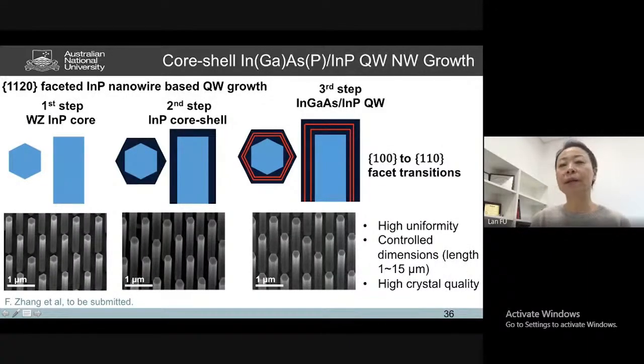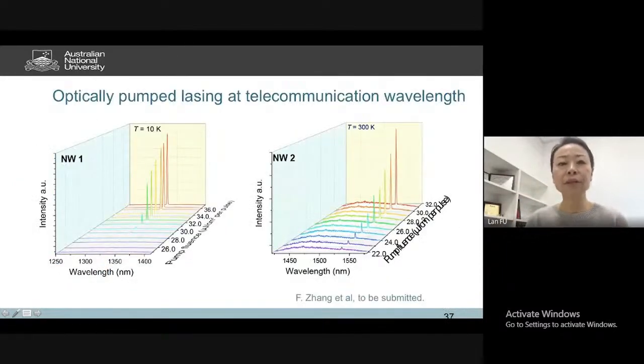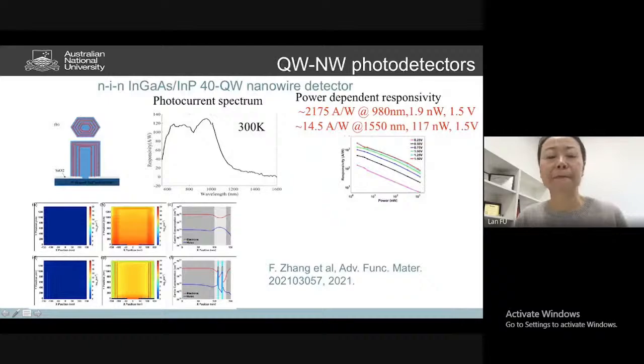Based on the recipe, we can now introduce indium gallium arsenide again, which turns out to be quite uniform and also with good dimensions. So we can control them to grow longer nanowires in this way. For this one, we pump them harder. We pump them using a laser, and we can achieve room temperature lasing, very beautiful lasing at around 1.55 micron. This is coming from our core-shell-based substrate of indium phosphide and then grown indium gallium arsenide.